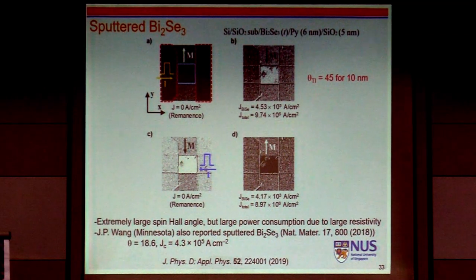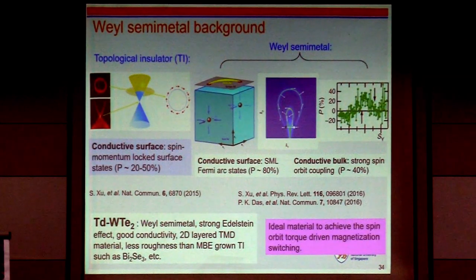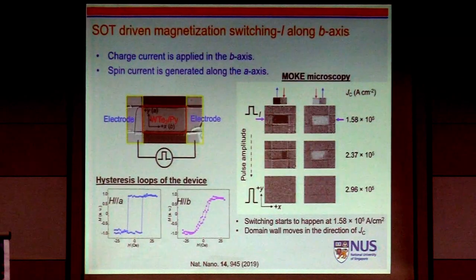So we are switching our material to a new topological material called Weyl semimetals. And this material, as the name stands for, is a metal. And not only the surface, the bulk also has a large spin polarization and large spin-orbit coupling. So it's predicted to give a very large spin-orbit torque. So we are doing the same measurement. We chose this tungsten ditelluride and put the permalloy on top and then patterned the device.